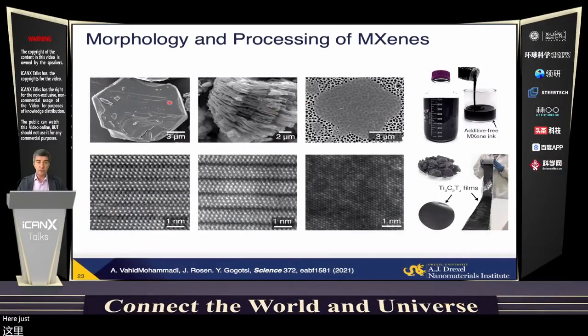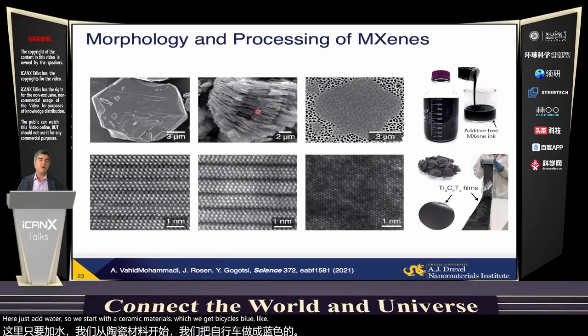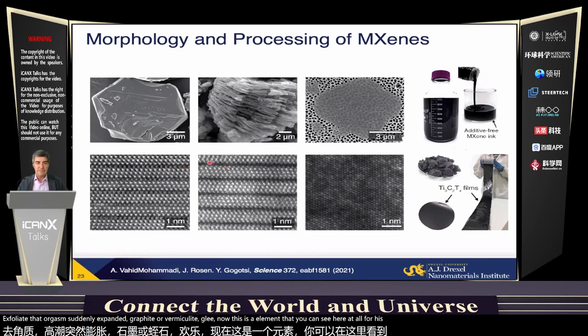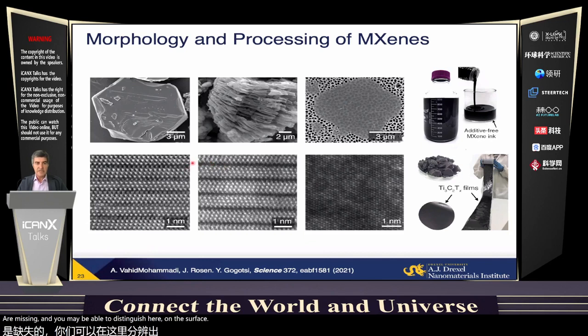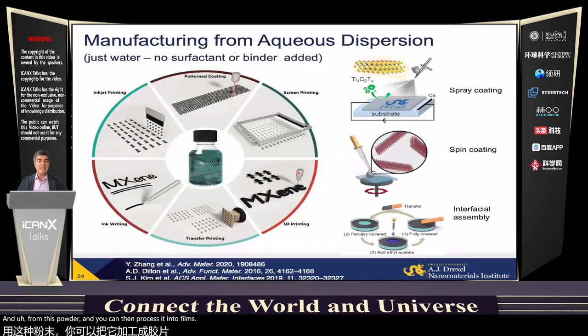Here, just add water. So we start with the ceramic materials, we etch it, we get particles that look like exfoliated or thermally expanded graphite or vermiculite clay. Now, this A element that you can see here, a row, for example, of aluminum atoms, are missing, and you may be able to distinguish here on the surface terminating atoms. And after that, if you intercalate it, or sometimes if you use, for example, lithium fluoride in etchant, it's enough just to shake the bottle. You will get a colloidal solution of single or few layer flakes and from this powder, you can then process it into films. As I mentioned, even without adding any surfactant or binders.